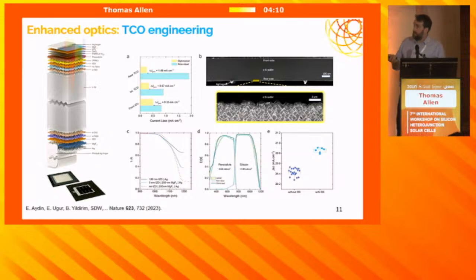And that's coming from an optimization, of course, at the top, where we thinned down the TCO, increased the thickness of the magnesium fluoride, and very much tried to decrease the thickness as much as possible of the C60 ETL. And then at the back, we implemented a rear reflector design with the magnesium fluoride displacer, which I'm sure a lot of you are familiar with. And so both of these optimizations together conferred about a 1 milliamp advantage to both subcells. And so now we're getting towards or even slightly above 21 milliamps for the tandem, which is more or less current matched.